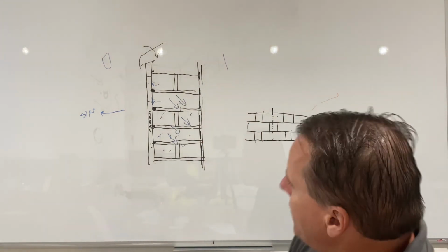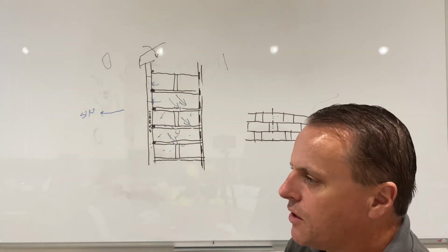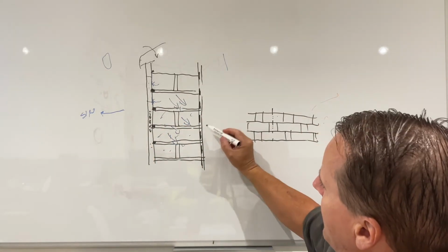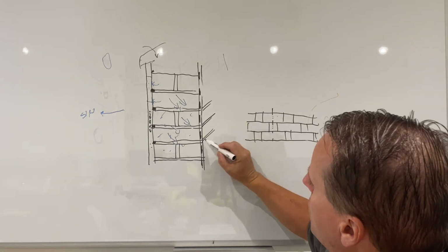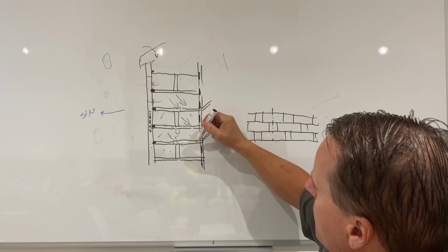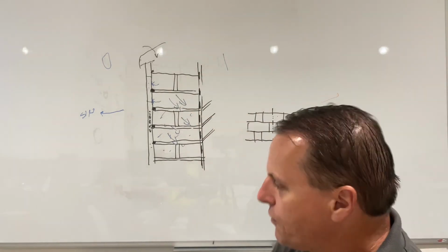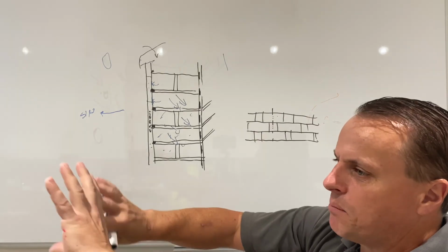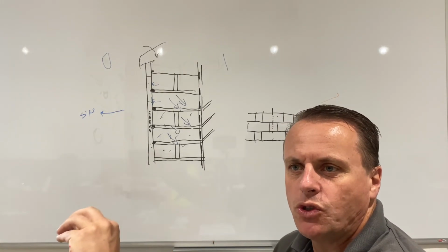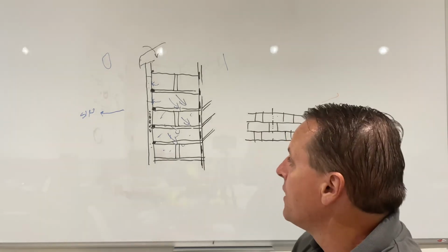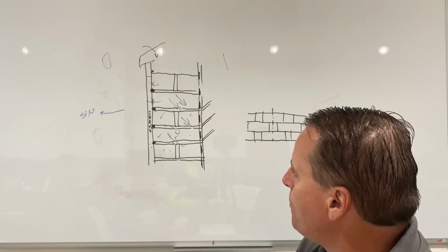And what we did is, because this area was blown, we took off quite a big area of plaster on the inside of the wall. And within days, we could start to see all of the joints in the brickwork. The moisture built up so much, it pushed the bitumen coating off the joints. So you could see a whole wall where everywhere that was black was a brick and everywhere that was a joint was the mortar colour. So really good example of how not to repair a wall.